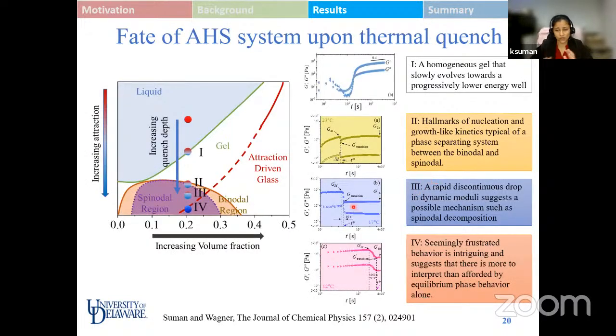So now with all these rheological results in hand, we try to analyze our results and understand what might be happening in the microstructure, which gives rise to such interesting rheological results. We first saw that at temperatures very close to the gel point temperature, there is a continuous increase in the value of modulus, which suggests that the system is slowly progressing towards a lower energy well, and it is lying in the gel-like region, which is marked by region 1 over here.